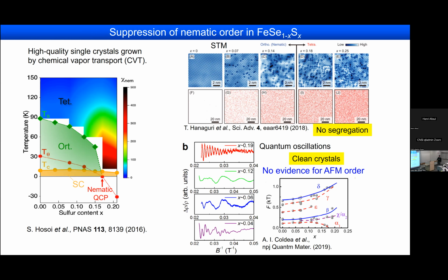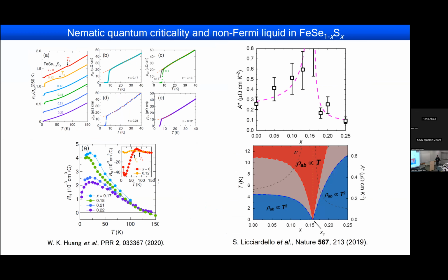And you can even find very clear quantum oscillations in a wide range of sulfur compositions, meaning that we have a pretty clean system. So this is actually very important to study the intrinsic physics in these materials. And this nematic quantum criticality can also be seen in the transport measurements. And we can have this very linear temperature dependence of the resistivity down to a very low temperature if you apply a strong magnetic field to suppress superconductivity. And one can find the very unusual temperature dependence of the Hall coefficient.